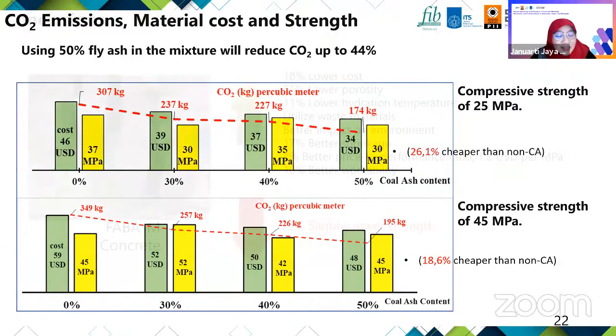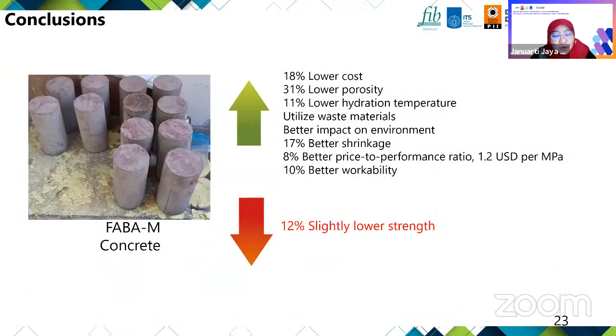And finally, these are the conclusions. As we applied high volume fly ash in the mixture, we obtained many good results. Even though we have a slightly lower strength, we can manage that in future research. We get a lower cost at least, and a denser matrix, low hydration temperature, and better shrinkage. If we control the water content, it is very important. And of course, we can contribute to sustainable concrete.